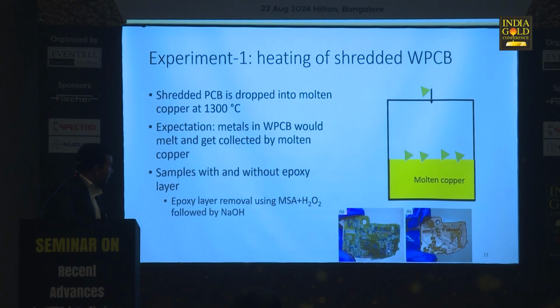The first one is, since we have this PCB, there is also a recipe to remove the resin from it, so you can further strip it and have just the fiberglass and the resin. So the structure is you have fiberglass, then you have the printed electronics, and then that is with the resin. So you can strip the resin as well. So the first thought was that you can just melt some copper, drop this PCB in, and then the metal should melt and go into your copper, and then you can process that copper later.